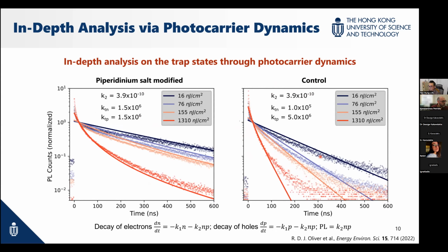So what we found is at the interface, we have very different carrier dynamics. What it means is we do not have the same amount of charge carriers of opposite polarity. Basically, electron and hole concentrations are not the same. This is quite common to see in a perovskite because perhaps you heard about the stoichiometry of a perovskite of a few hundred nanometers. The composition may not be the same. This is one thing that may cause this kind of uneven charge carrier distribution between opposite polarities.